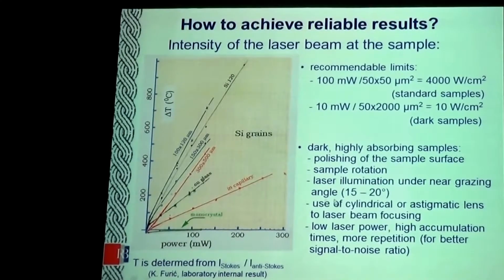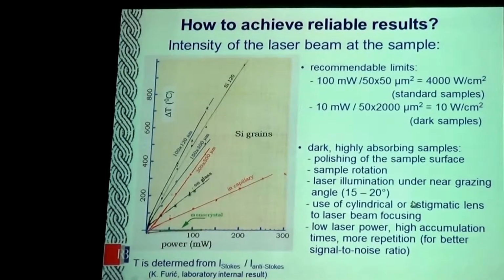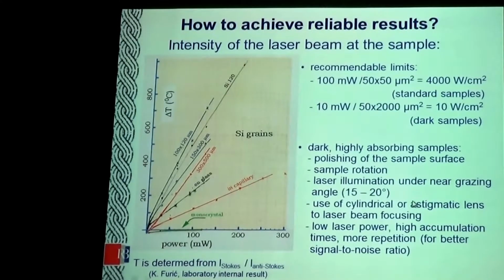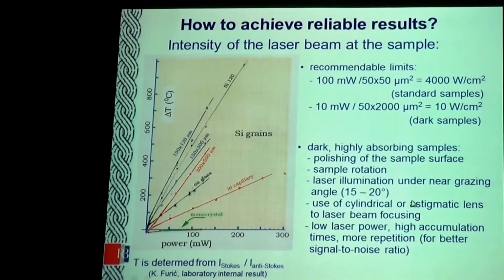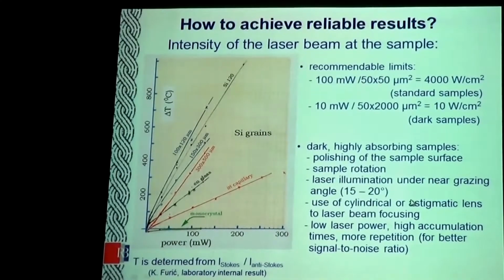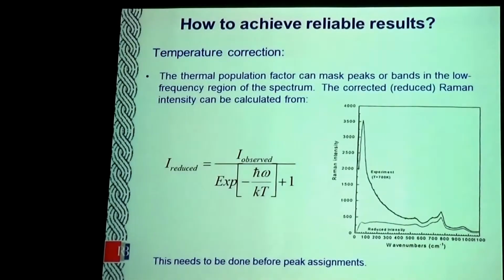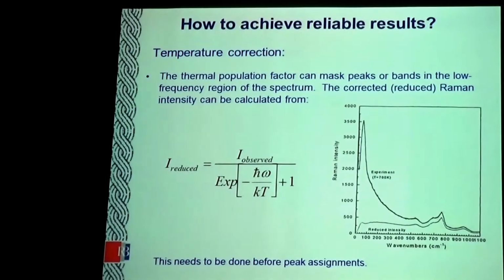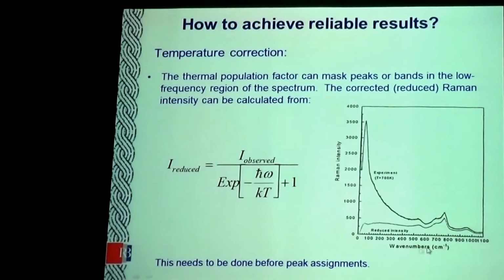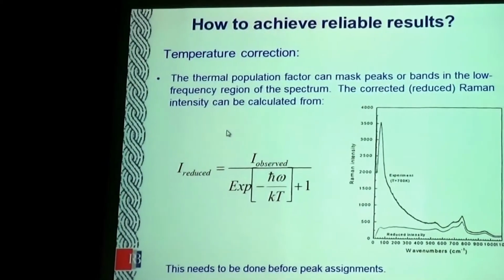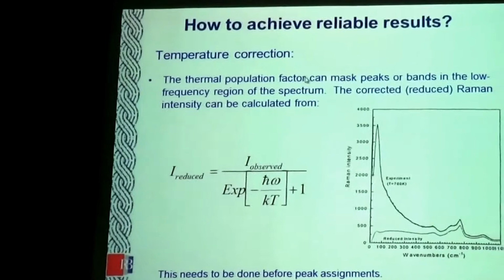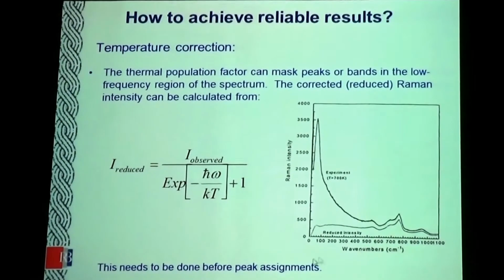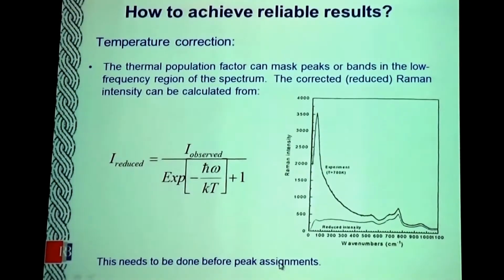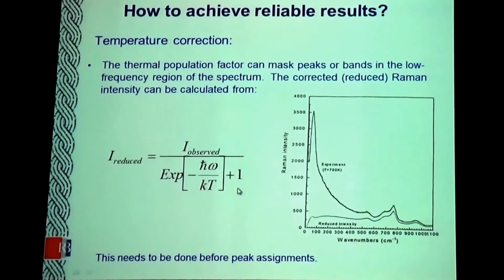You can use also cylindrical lenses to produce a line focus, not a point focus. Then you will avoid heating. And there is the other thing - if we do high temperature measurement, we should check the thermal population factor and correct the spectrum before we do any peak assignment.